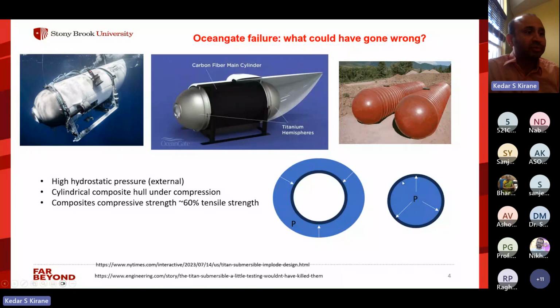But if you reverse it from inside to outside, like shown on the left, which was the case with the OceanGate, the entire structure is under some kind of compression, not uniaxial, but multi-axial compression. And that is often a limiting factor for composites design, because they consist of these long fibers. So when these are long, when they're compressed, they tend to fail by a micro buckling instability. And that's what I will talk about mostly today. So many people believe that this could have been the failure mode for the OceanGate, the compressive failure of the cylindrical hull of the submersible.